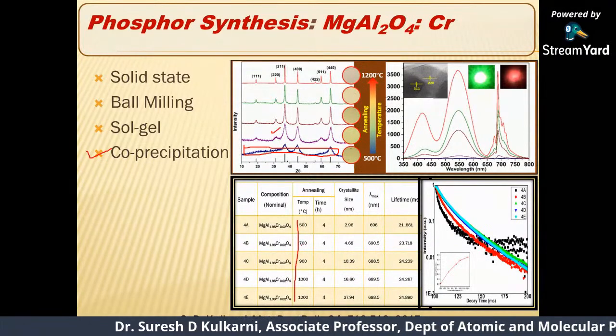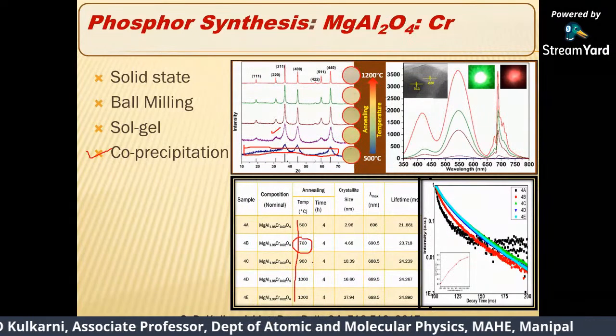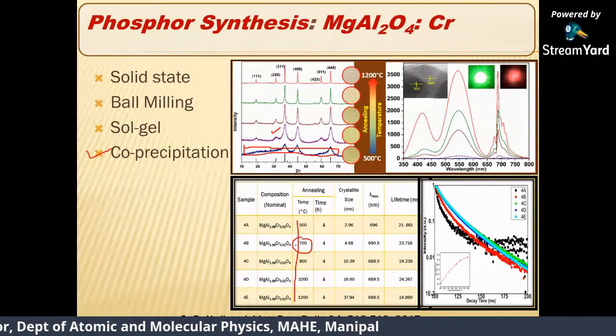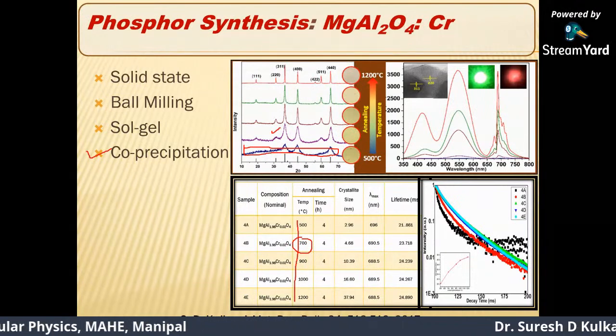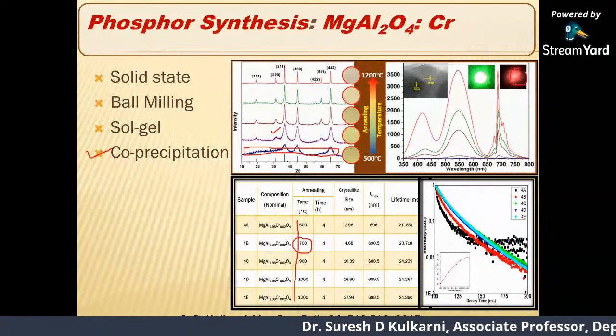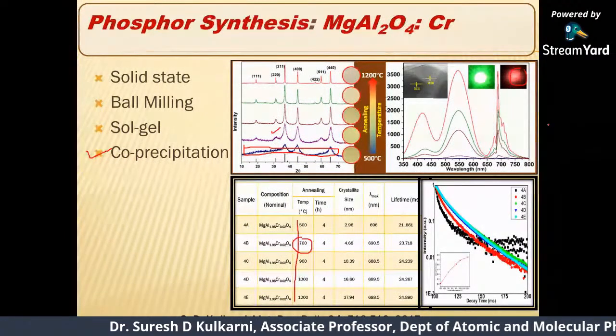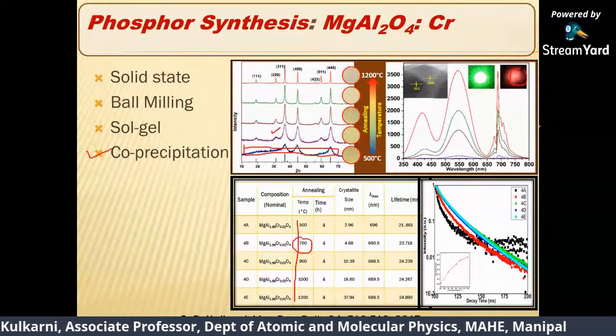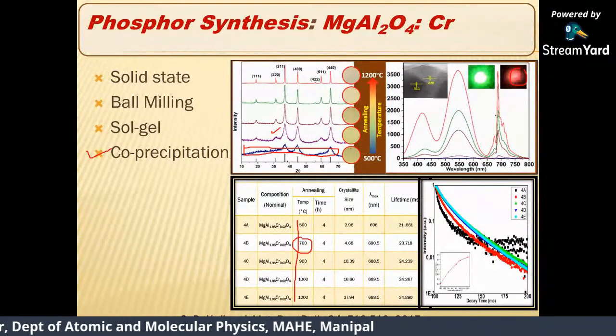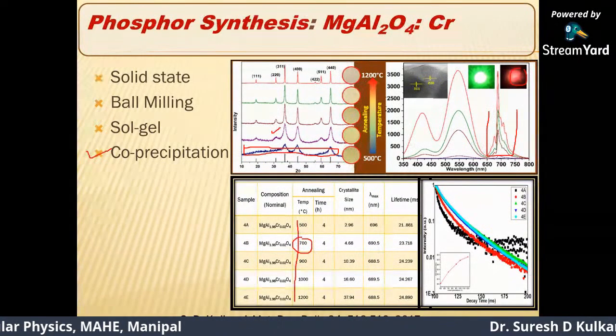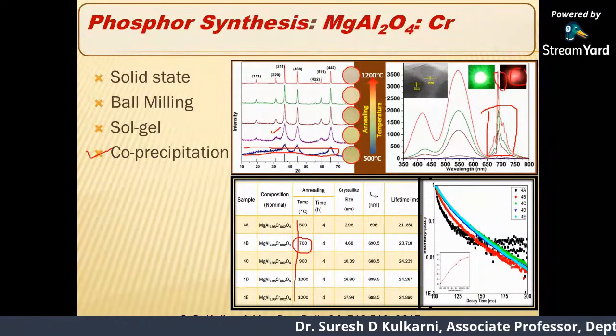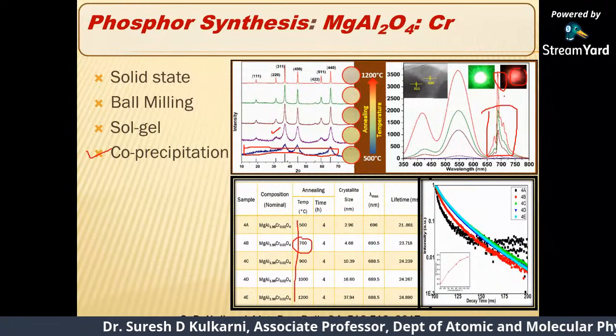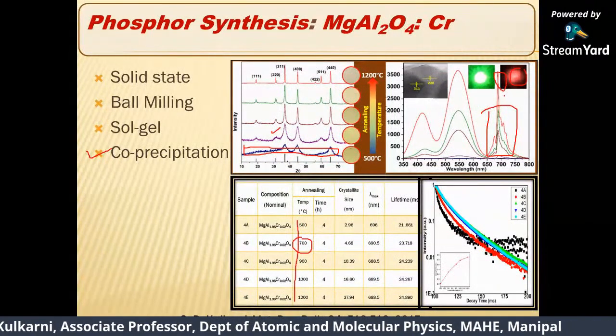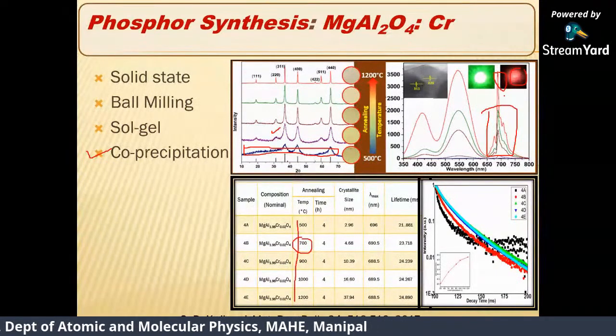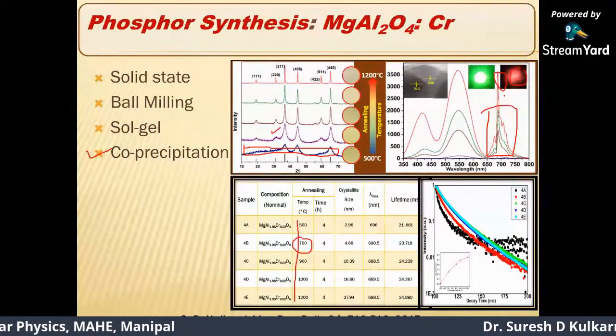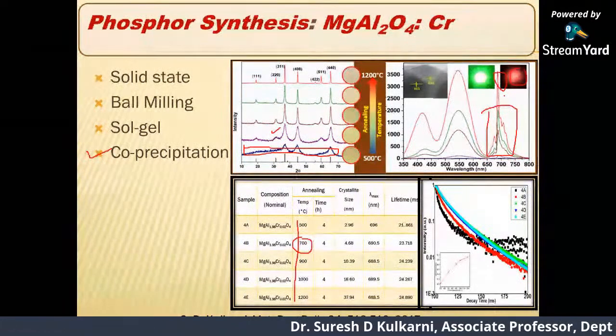But here, yes, we can say at 700 degrees onwards the material is formed, and we understand that 700 is the minimum required temperature, and when we anneal to higher and higher temperature, you can see a good nice red emission can be obtained from our material. So this is a red phosphor. It gives emission in the NIR region around 700 nm, and you can see the emission spectra here, and a nice sharp red emission can be observed here. So what we understood from this is that a temperature of 700 and above is required, and 1200 is giving you better results. That means higher sintering temperatures are required.